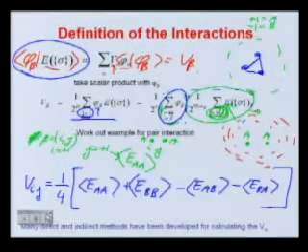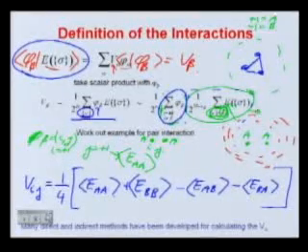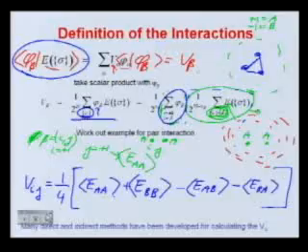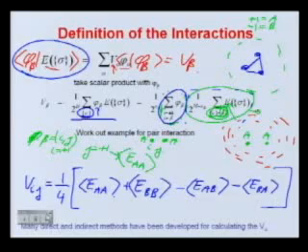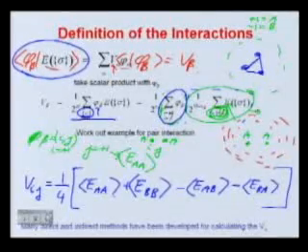If your system is symmetric, if I and J are equivalent, then these are the same. If you have translational symmetry between I and J, then you'll get something like -2 EAB. Those of you who've seen regular solution thermodynamics may recognize this as an effective prefactor in the enthalpy of mixing. You'll get something like the AA interaction plus the BB interaction minus 2 times the AB interaction. But just pointing that out, it's sort of interesting.